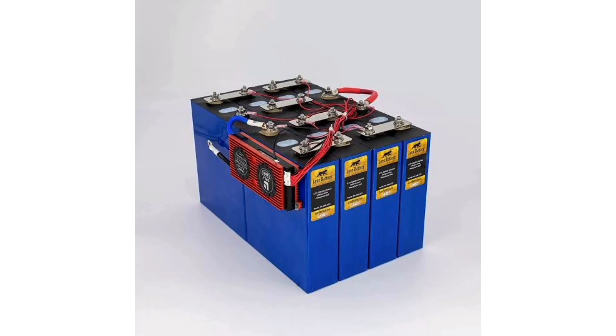When it concerns safety, lithium iron phosphate has good thermal stability. That means they stay cool in high temperatures — they don't experience thermal runaway because the phosphate cathode will not burn or explode during overcharging as the battery remains cool. Lithium-ion does not have the same safety advantages. Its energy density causes the battery to be unstable; it heats up faster during charging and it can experience thermal runaway.